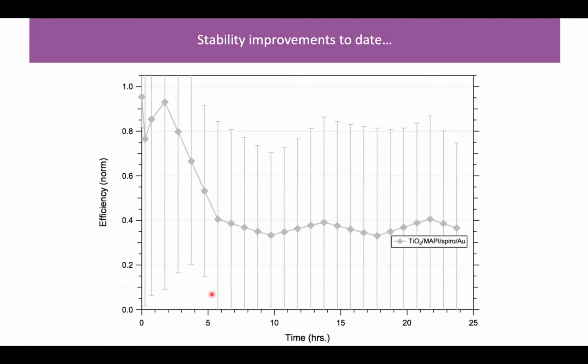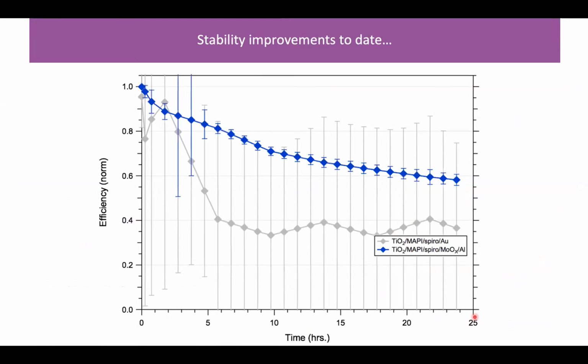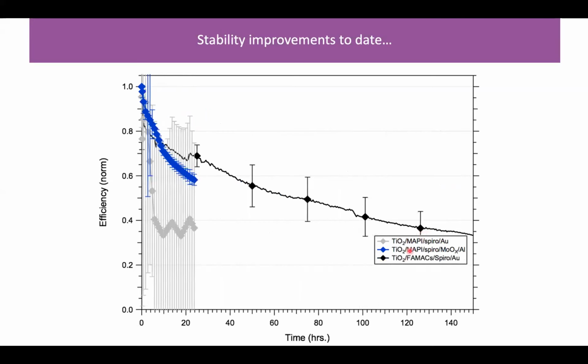But this is a set of data that I think is instructive. When we started our metal halide perovskite work, almost 6 years ago now, this is what we got for stability. And you will notice that the time is measured in 25 hours. That's not going to make a product. But we realized some things about the contact interface, and we certainly got better at making devices, because you can see the statistical spread was reduced. But again, these devices died relatively rapidly. The active layer people: you'll notice I went from this prototypical MAPI to this triple cation system, which is a combination of methylammonium, formamidinium, and cesium. We made slightly better devices, and we could at least measure them for long periods of time. So now we're at 150 hours or so.